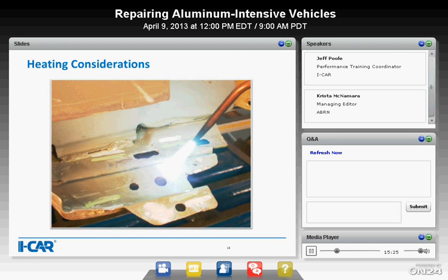So if heat's being used, let's make sure we identify any recommendations or guidelines that there are. As a general rule, we do not want to exceed 450 degrees Fahrenheit. That's your absolute maximum. Now, there's a property called annealing. Annealing is something that happens to metal whenever you heat it beyond a certain temperature. It'll permanently soften or change the properties of that material, and we're just not going to get it to go back where it was. For most of your aluminum alloys, annealing temperatures start at about 650 degrees and go up from there, again, depending on the alloy. So the 450 degrees and below is a safe area to live in.